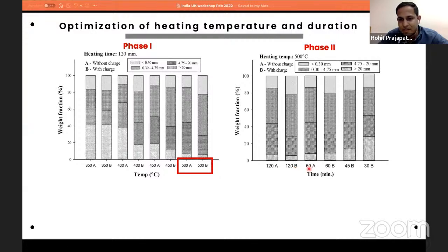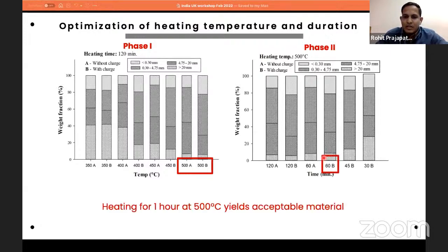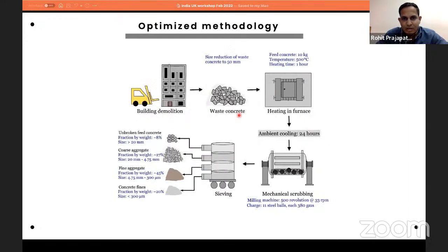From this phase, we could see that even 60 minutes is enough to weaken the concrete to produce acceptable materials. So this is the optimized process where we reduce the size to 50 mm and then heat it for 1 hour. And after cooling, it is milled in a milling machine, and then you get these three products, which are coarse aggregate, fine aggregate, and concrete fines.